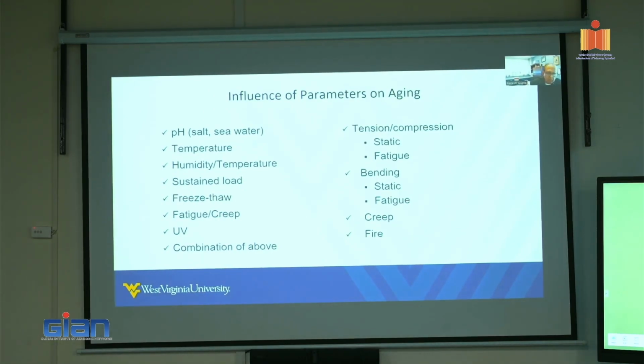Surprisingly, moisture turns out to be a very harmful agent by itself. It causes physical changes, such as lowering of the glass transition temperature, and what that does is to plasticize the matrix. You can have significant changes, lowering the Tg with a 1 or 2% increase in the concentration of moisture in the polymer.